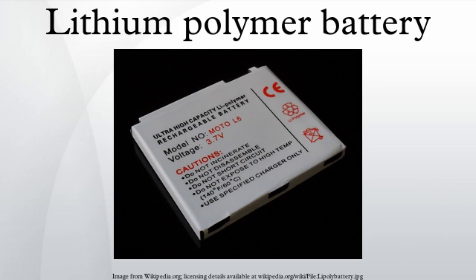In addition to this, the positive electrode can be further decomposed into three parts: the lithium transition metal oxide, a conductive additive, and a polymer binder of polyvinylidene fluoride. The negative electrode material may have the same three parts, only with carbon replacing the lithium metal oxide. Therefore, even if a bare, unfinished cell lacks a polymer separator or any liquid or solid electrolyte, it may still have a polymer component in the active materials of the electrodes. This polymer, however, is just a small fraction — typically less than 5% by weight — and does not participate in the electrochemical reactions, being only useful for binding the active particles together to maintain good conductivity, and helping the slurry mix adhere well to the copper and aluminium foils that compose the current collectors of the battery cell.